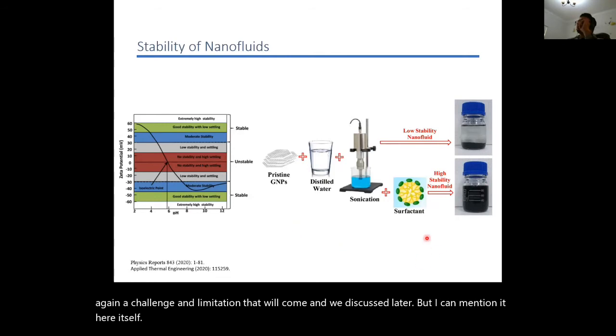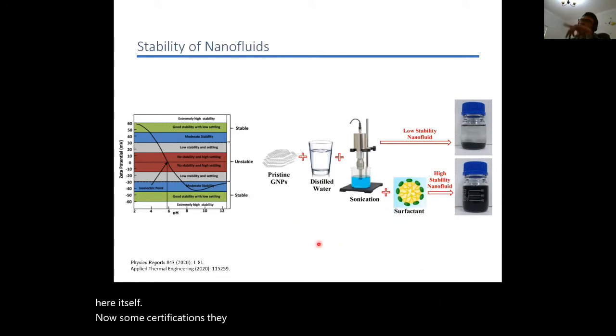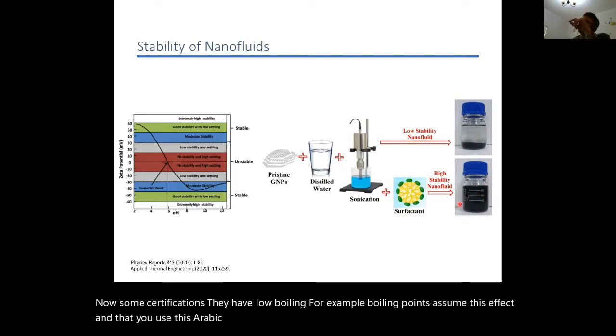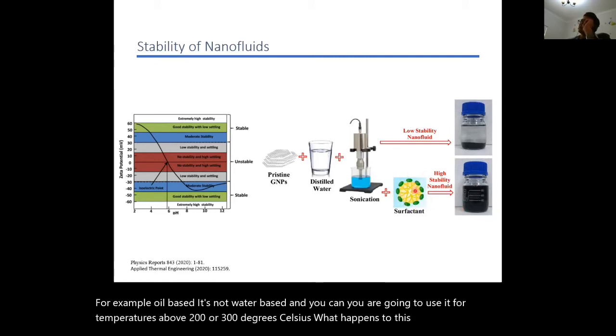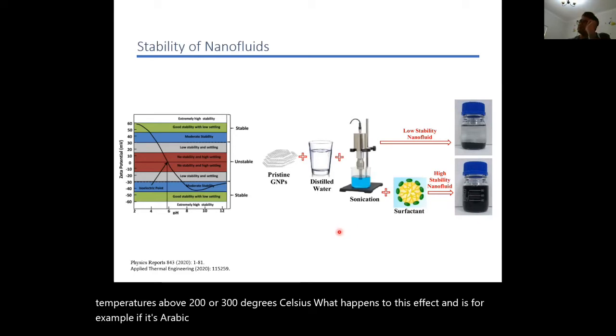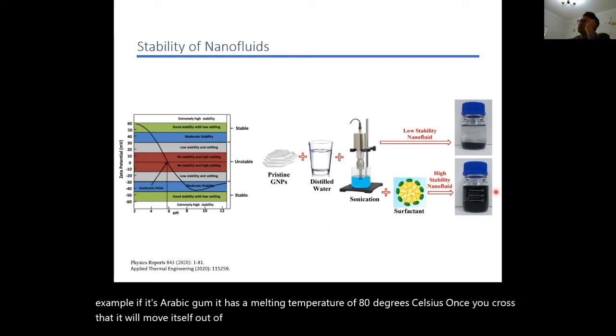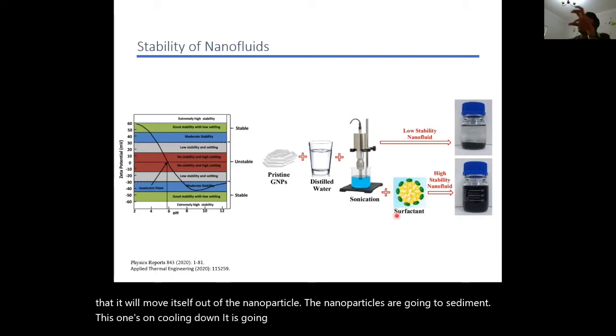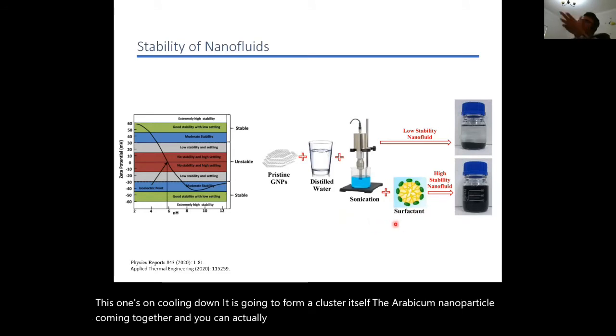Some surfactants have low boiling points, for example. Assume the surfactant that you use is Arabic gum for the nanofluid, and you're going to use this nanofluid, for example oil based, not water based, for temperatures above 200 or 300 degrees Celsius. What happens to this surfactant, if it's Arabic gum, is it has a melting temperature of 80 degrees Celsius. Once you cross that, it will move itself out of the nanoparticle. The nanoparticles are going to sediment, and on cooling down, it is going to form a cluster itself, the Arabic gum and nanoparticles coming together, and it can actually clog your systems rather than giving you a positive result.